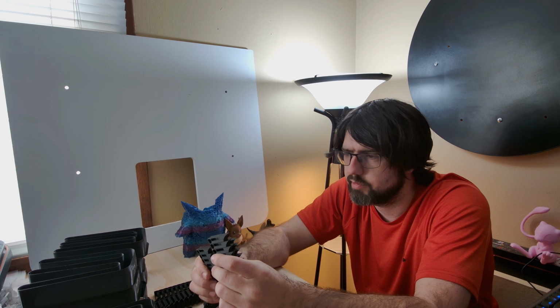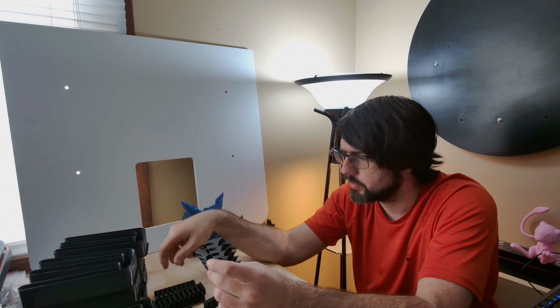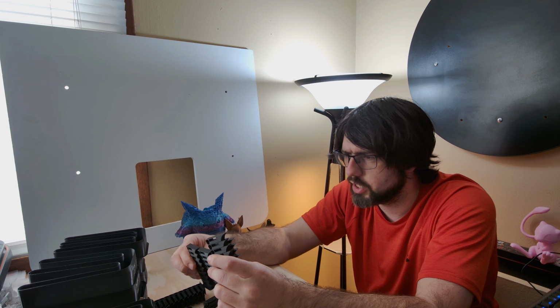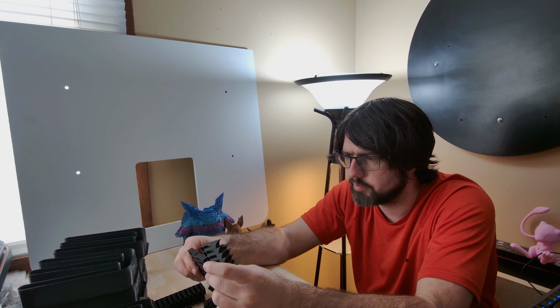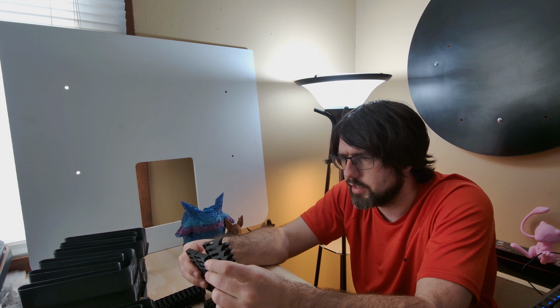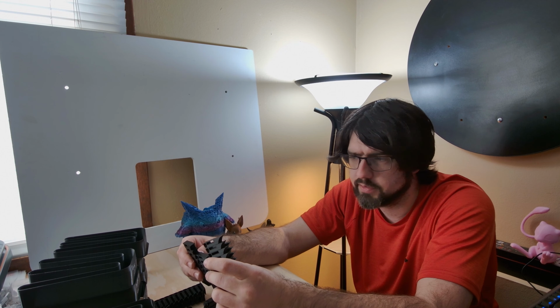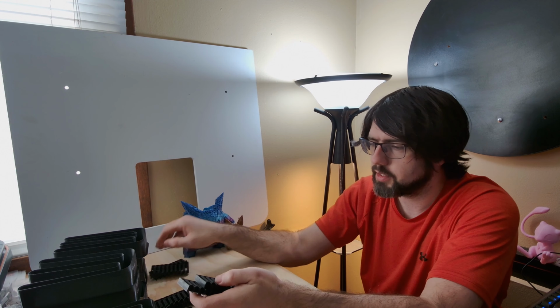Completely gone by 240. It did print out all the way up to 220 with no stringing, though it's a little bit more matte finish, but significantly shinier than the copper nozzle. The equivalent sheen is probably around the 230 as far as the PETG goes.